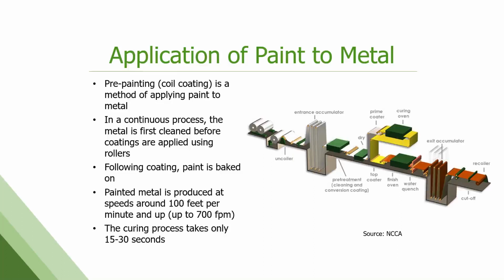From the time of paint application until the paint is completely dried and cured is only about 15 to 30 seconds. By comparison, your average automobile painting process at initial assembly takes 30 minutes to 2 hours. This is the quickest industrial coating process there is, and we're also applying the thinnest amount of paint of any industrial coating process on metal.